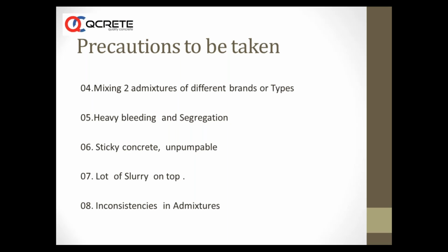So we hear customers talking about heavy bleeding. Heavy bleeding and segregation can happen because of coarser particles, gap graded aggregates, a complete repulsion of admixture by cement particles - meaning cement particles repel water and admixture in a very big way - and high amount of charges deposited. High dosage also can cause heavy bleeding and segregation.